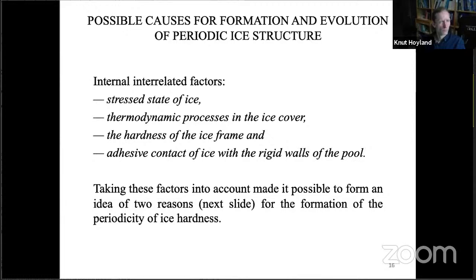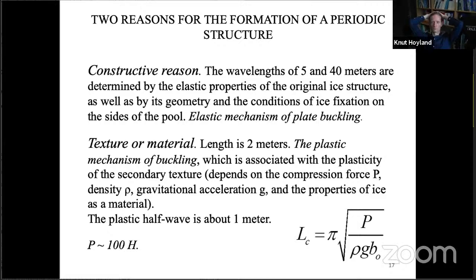From possible causes, authors would suggest concentrating on internal interrelated factors such as stress state of ice, thermodynamic processes in the ice cover, the hardness of the ice frame, and adhesive contact of ice with the rigid walls of the pool. Two reasons for the formation of a periodic structure. Constructive reason: the wavelengths of 5 and 40 meters are determined by elastic properties of the original ice structure, like the elastic mechanism of plate buckling. And the second one, texture or material: the plastic mechanism of buckling.